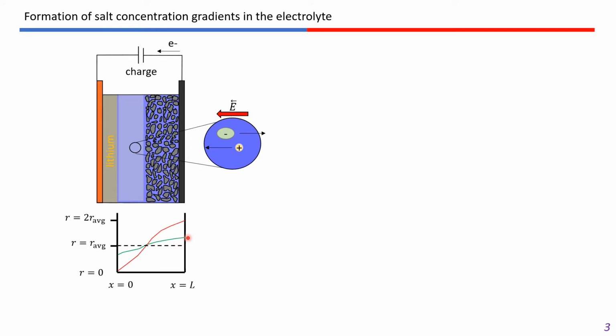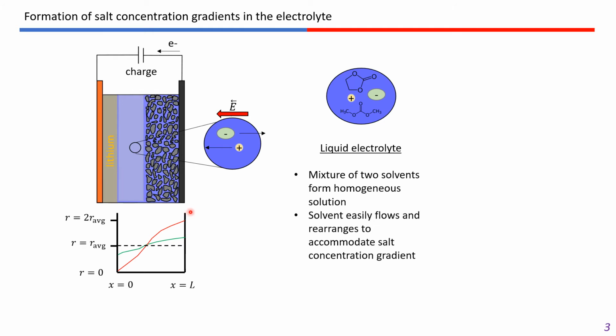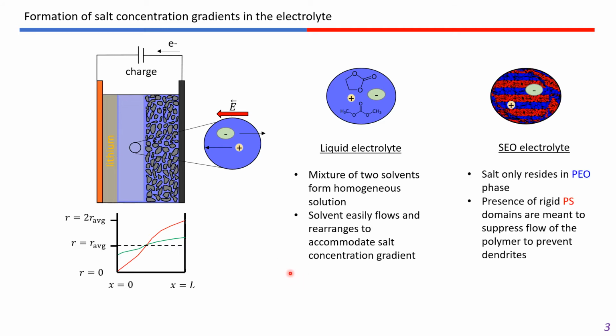And if we increase the potential or increase the current density, this results in an increase in the salt concentration gradient, where we expect a maximum value to be about twice the average salt concentration because the total salt concentration in the electrolyte must be conserved. Now, the formation of these salt concentration gradients is not too much of an issue for traditional liquid electrolytes because the solvent can easily flow and rearrange to accommodate the salt concentration gradient.